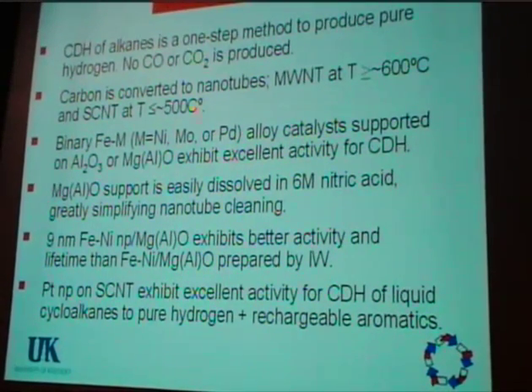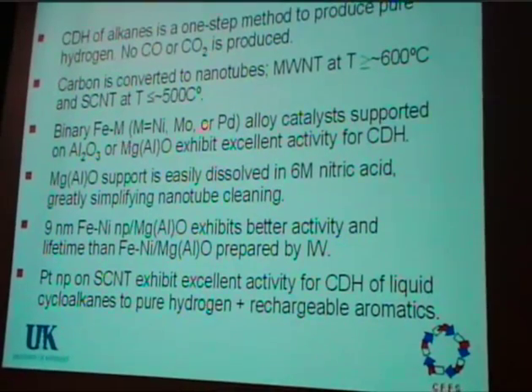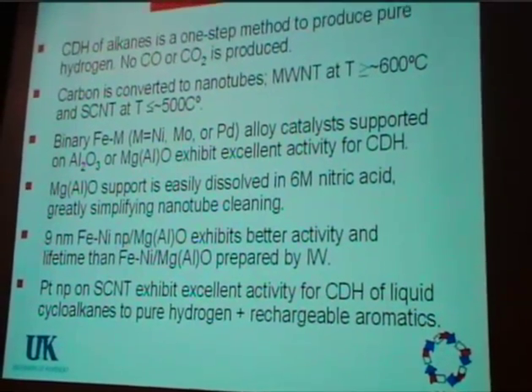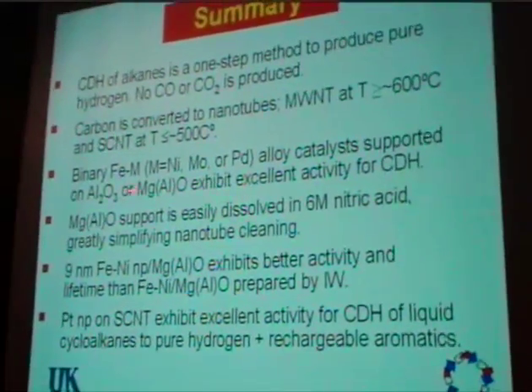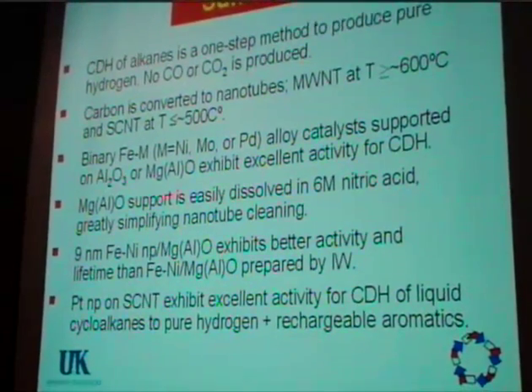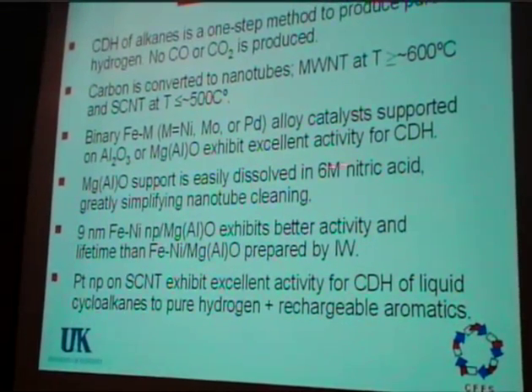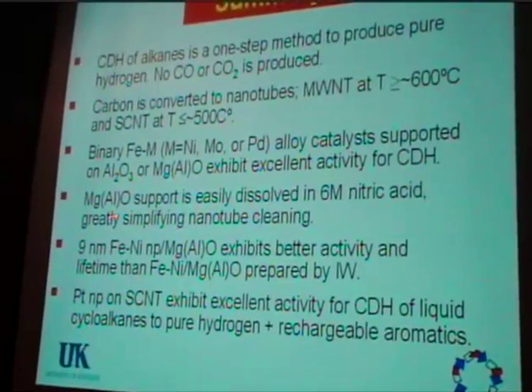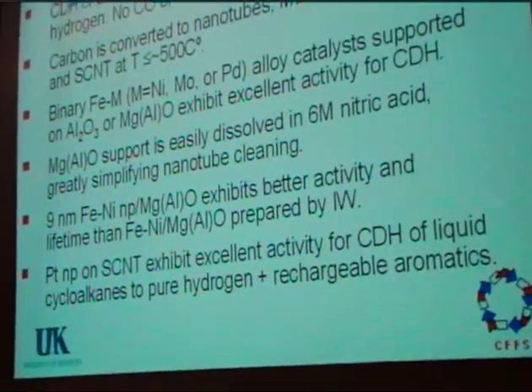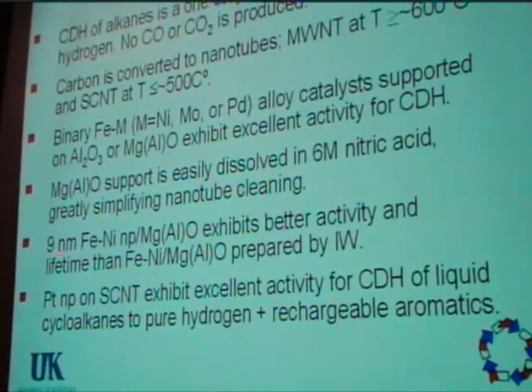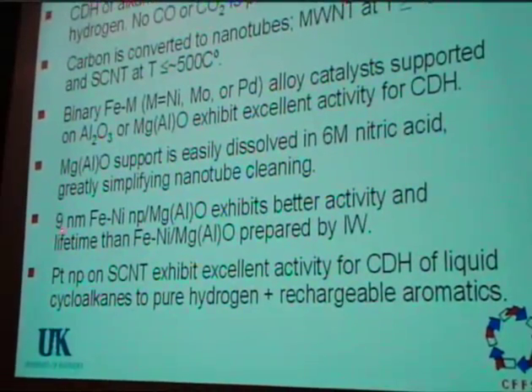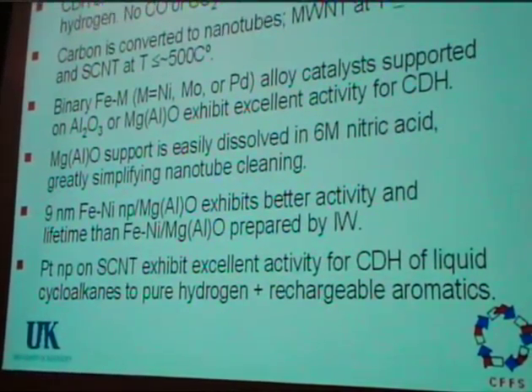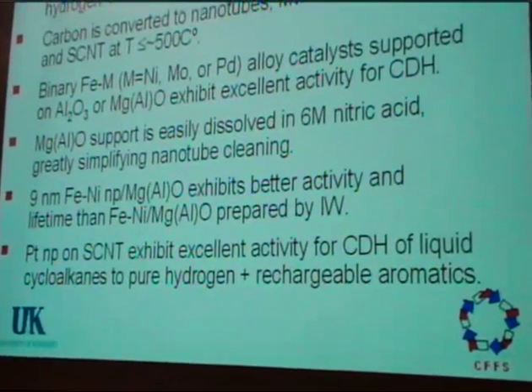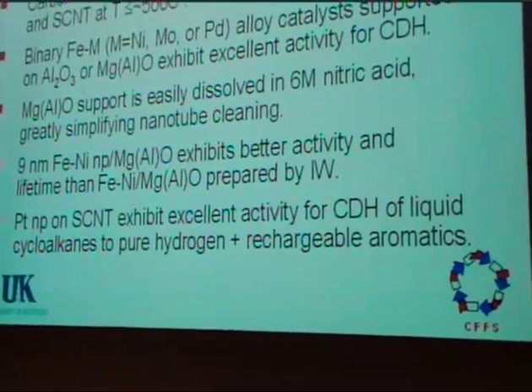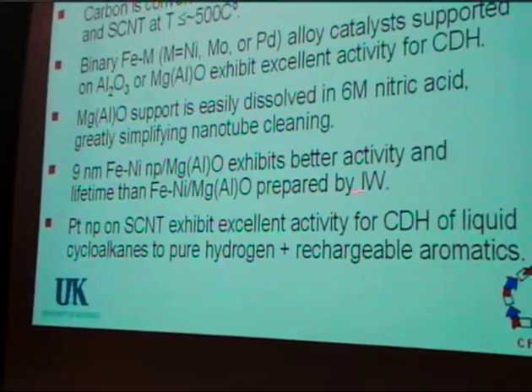They're iron-based. The iron nickel one particularly is cheap. Iron moly isn't too expensive. Iron palladium is interesting. Maybe you wouldn't want to use that. The magnesia alumina support looks preferable if you want to use the carbon nanotubes as a valuable byproduct, because it's very easy to dissolve and it makes it very easy to clean those nanotubes to impurities of greater than about 99.5%. Nanoparticles work better. They seem to be better by a factor of at least 3 or 4 in terms of the stability and activity compared with catalysts prepared by incipient wetness.